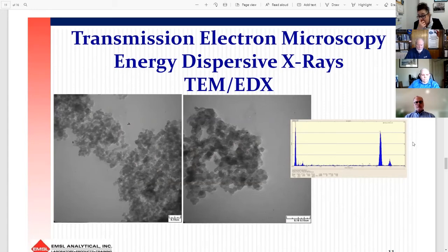But this is not as important for wildfires. I just added it because sometimes you get a very dark sample, and the client expects a large amount of char. And it's not char, it's soot maybe. And then the entire scope is different. So if it's not char, if it's not wildfire, that means it's a different type of contamination. That means it's not really an insurance claim for wildfire. So it's a little nuanced on how and where and why you would use TEM, if it's useful for some more extensive examinations.